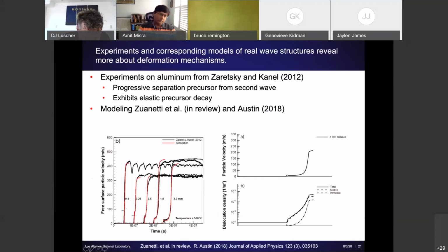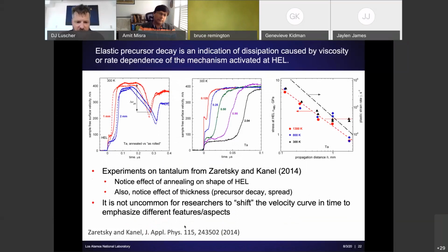But we also notice that the magnitude of the HEL is descending. That's often referred to as precursor decay. And these results on tantalum from Zaretsky and Kanel, I would encourage you to take a look at that paper, especially in the context of the homework problems I'm going to suggest in a few minutes. They characterize that decay very nicely in terms of the stress at the HEL and how it is affected by the propagation distance of a wave through a specimen. The point here, to connect this back to the main theme of the lecture, is that the structure of the wave is evolving as it propagates through the material.